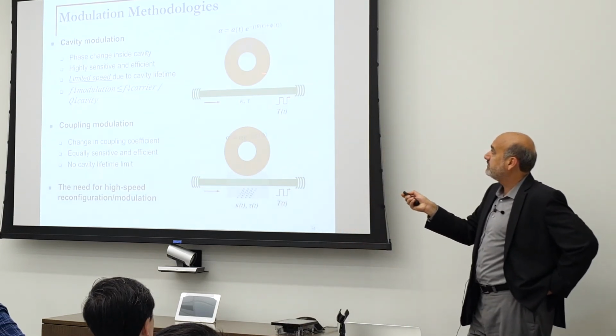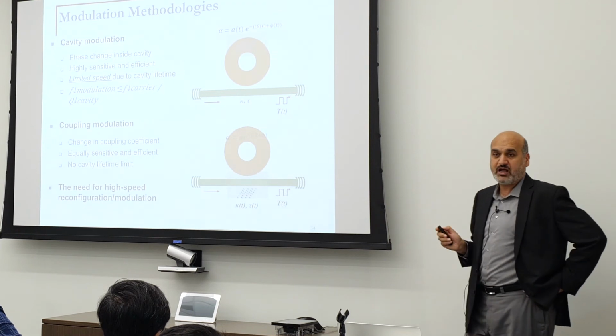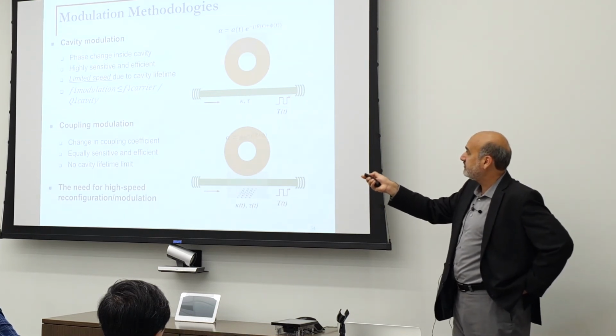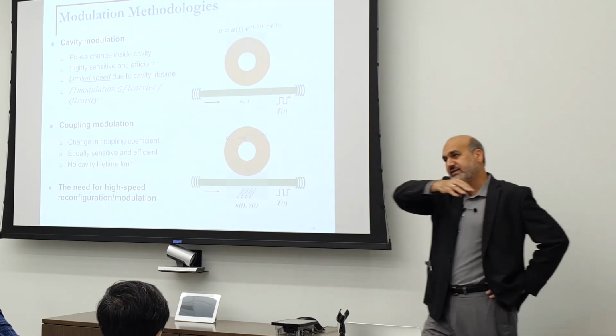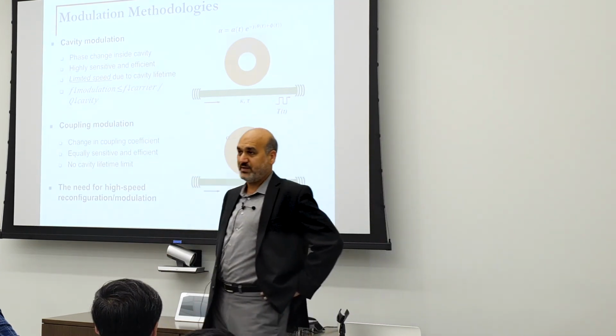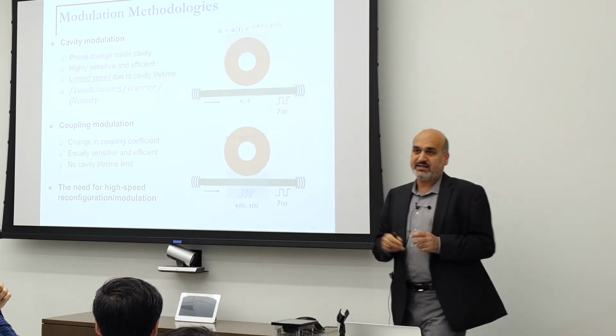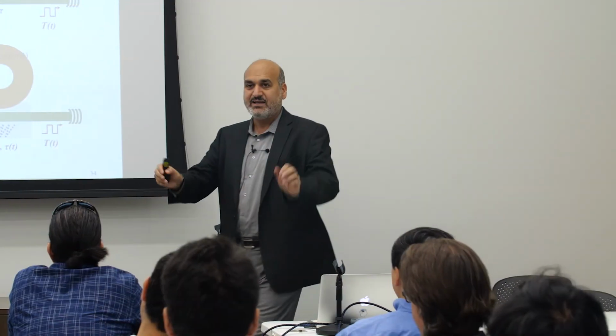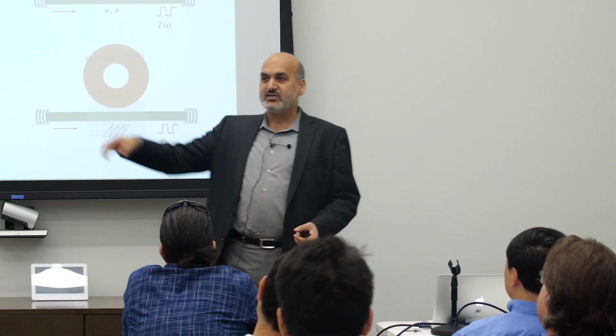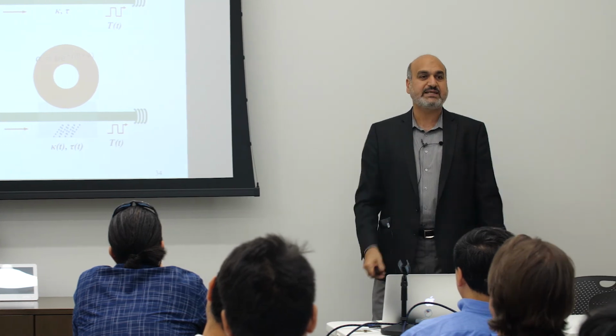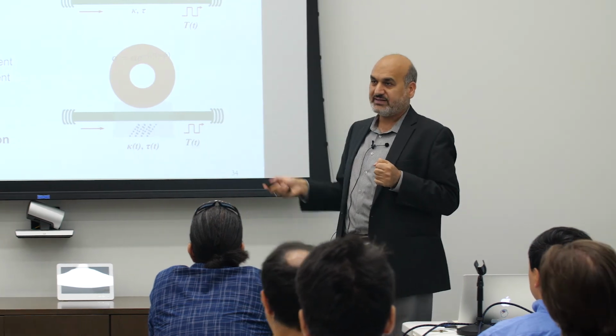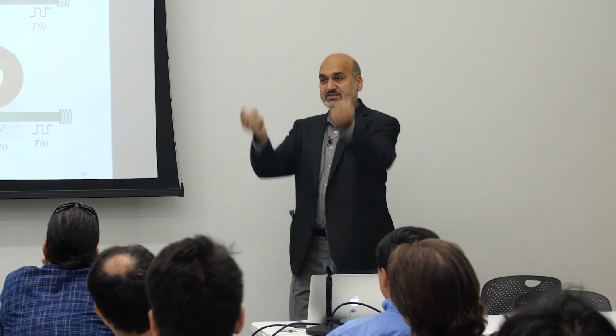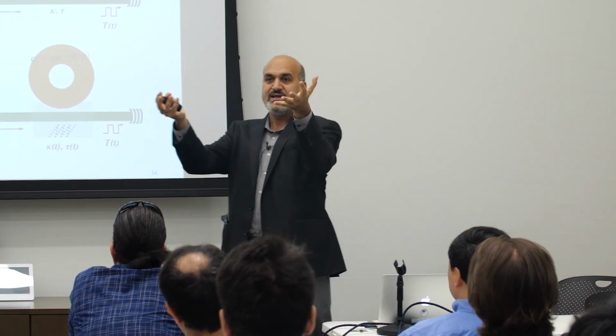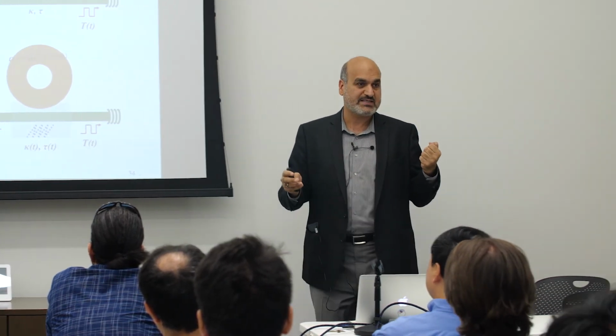The problem really is that if you make a very high Q, a very sharp resonator, a little change in its wavelength is enough for doing the modulation. But then a high quality modulator has a long photon lifetime, meaning that the optical beam stays there for a long time, and you have to wait until that is emptied in order for the next bit to be modulated. Just to think about a simple example, suppose you have a dam and you want some water in a channel. In one idea, you just empty the dam and fill it up again for each bit of water in the channel. That's what we do here. We fill up the resonator with photons. That's called resonance. We just empty it. That means off resonance. And we have to wait for this emptying to be done.